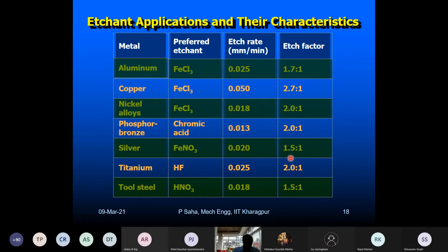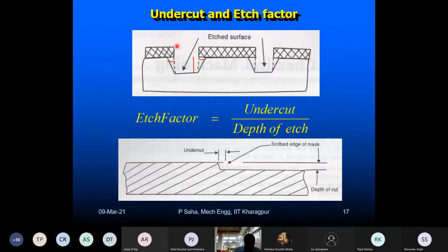Like in some cases it is 1.5:1. That means if you want to achieve a depth of machining of 1 millimeter, from the mask tip you will have 1.5 millimeter side machining. In some cases it is as high as 2.7:1. So depending upon the etch factor, and if you know the depth of etching, knowing the dimensions, this extra dimension coming into the final machining you can restrict by restricting the mask opening. Suppose the intended dimension is 10 millimeter, so you don't make the opening 10 millimeter. Or you make the opening slightly less, because you know some additional dimension we are going to achieve through the side machining process. Otherwise we will lose our desired dimensions.